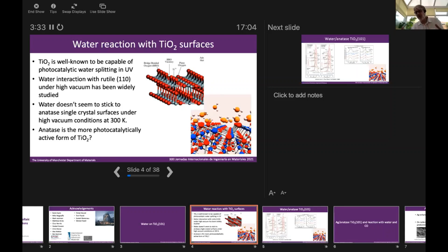And you leave that for anything between a few seconds to a few hours. And then you pump away the gas and then you analyze your sample. So it's a kind of post-mortem study. You measure your sample before exposure, you measure again after exposure, and you look for the differences. So this was done with an anatase crystal. And the strange thing was that although anatase is the most photocatalytically active form of titanium dioxide, water didn't seem to stick at room temperature.